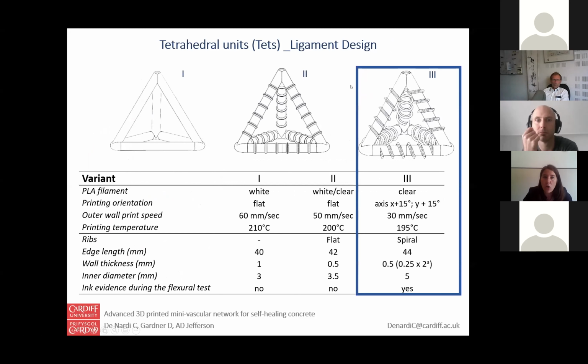At the beginning, all of them were printed flat, but then we decided to change the orientation of the printing in order to avoid anisotropies along the ligaments, such as delamination or differences in strength. So basically, we were looking for something which is brittle, but strong enough to survive the mixing phase, to be completely impermeable, and able to have very good bond properties with the concrete. And we reached the point with the third variant of the TETs.